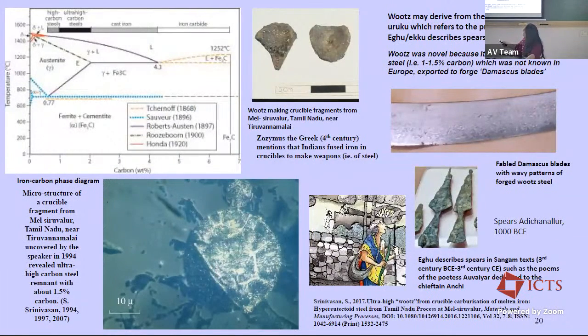And then, of course, I touched upon wootz steel, and I showed some of the evidence from some production sites that I had been looking at. And this is quite interesting because in this particular phase diagram, you can see how many people's studies have contributed to building it right across the late 18th to 19th century. And so now we understand better what actually causes the properties to improve, what happens when you add carbon to iron. I spoke about wrought iron, which typically has less than about 0.04% carbon, and that's very ductile, so it's used for forging quite extensively.